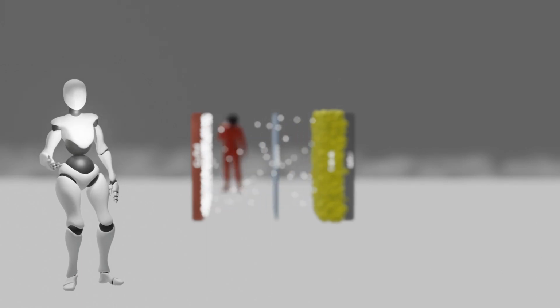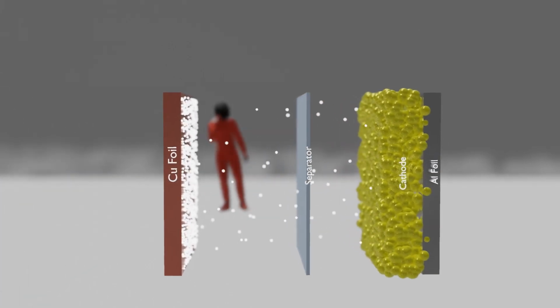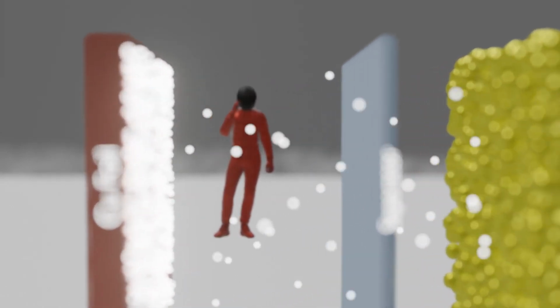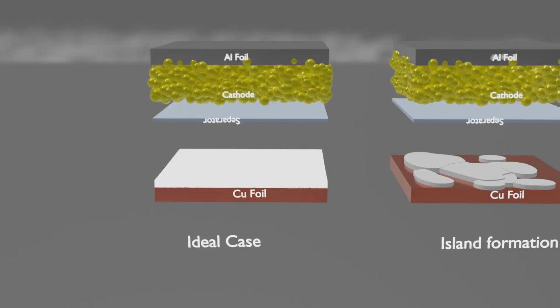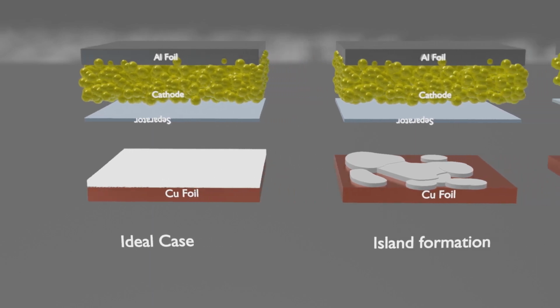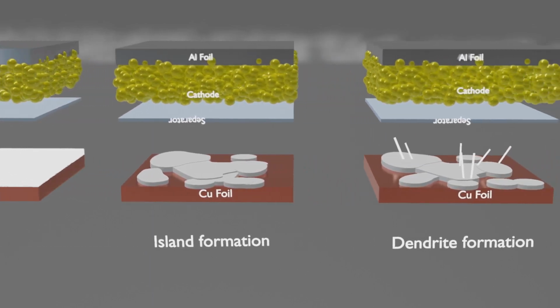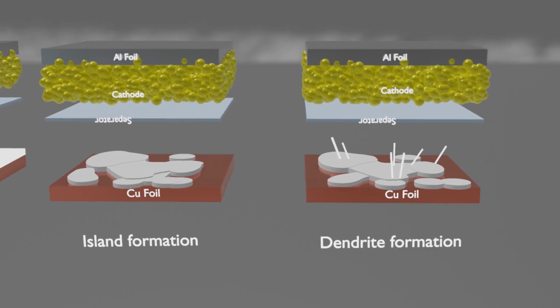Of course it does. When conventional graphite anode materials existed, lithium ions accumulated inside the graphite layered structure, but now they have to form a uniform lithium layer on the bare ground. Ideally, a uniform lithium metal layer should be formed, as shown in the animation. However, here and there they will grow in uneven layers, or even in the form of pointed dendrites, that is, in the shape of a spear.